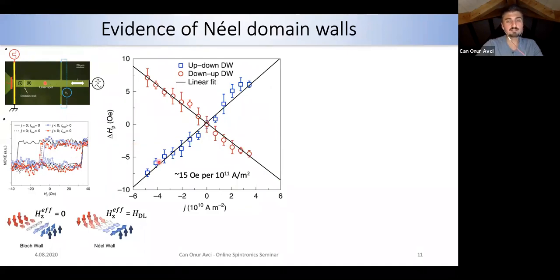The delta propagation, so the propagation field difference, linearly scales with the injected current. And when I reverse the domain wall polarity, so now I'm measuring down-up, then that effect reversed as well, which means that that's a clear effect of the current on the domain wall.